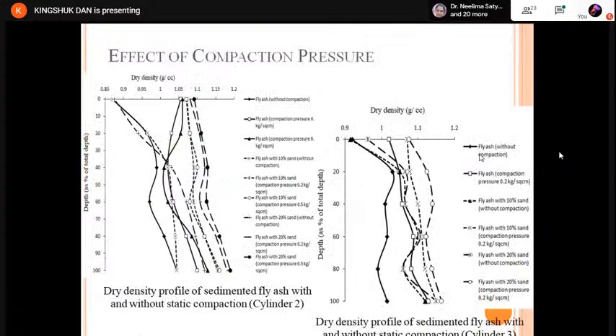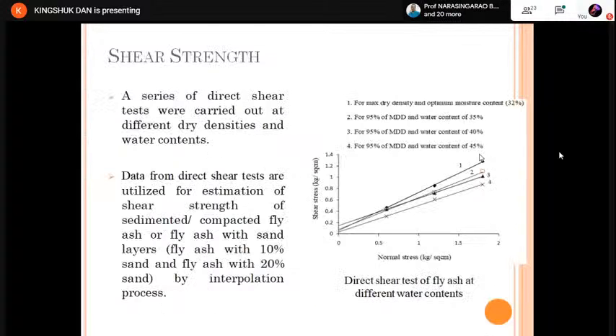This is the effect of compaction pressure. You can see in the upper layer and lower layer there is an increase of the dry density for both cylinder 2 and 3 due to the mixture of sand, and in the upper layer this increase of the dry density is very appreciable. But in the bottom layer, it is not as much as the upper layer, but we can see there is an increase of the dry density. So compaction pressure is giving good results to increase the dry density. In both cases we can see it is generally a 20% increase in the upper layer for cylinder 2 and 10 to 17% for cylinder 3.